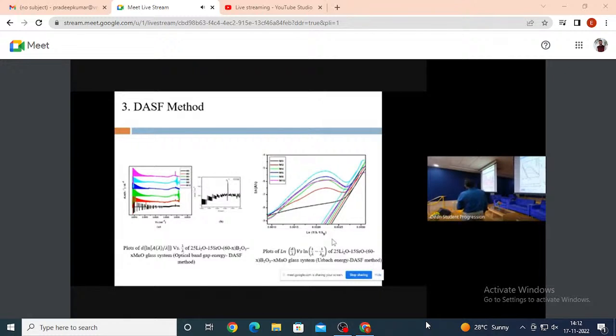From these plots, I have measured all the indirect bandgap values and tabulated them. From this spectra, the same trend was observed. Whatever trend was observed in the Tauc method and ASF method, the same trend was observed in this method for indirect bandgap values. That is, the indirect bandgap values decrease up to 0.8 mole percent. Later, the indirect bandgap values increase.